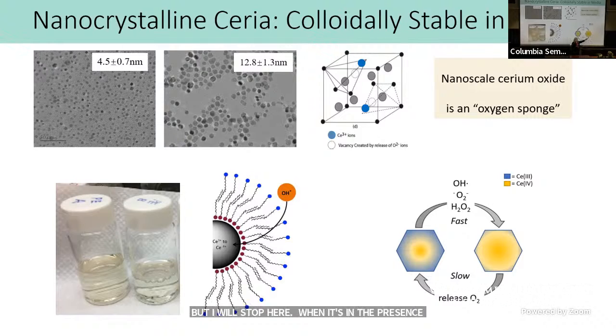It's very aggressive at pulling those oxygen atoms out of a biological environment. And it's a cerium 3 to cerium 4 conversion. But over time, it reacts with donors in the biological environment. It goes back to its stable cerium-3 form, which is what it likes to be in ambient conditions in the body. So it's reactive enough, but then it holds onto it, buffers it, and then eventually recycles back. The recycling time can take up to about 1 to 3 weeks, and then it goes back to being reactive.